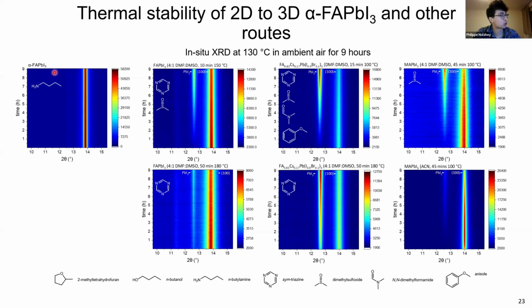And the molecules, which are shown here, are a different measurement. They're from a TD-GCMS measurement. So it's a thermal desorption gas chromatography mass spectrometry unit. So essentially, we just look at what is residual in the films and analyze that. And we find that for the 2D to 3D, the only thing which is residual is the butylammonium, to be fair, which is from the 2D phase. But we didn't actually manage to resolve that in the solution NMR.